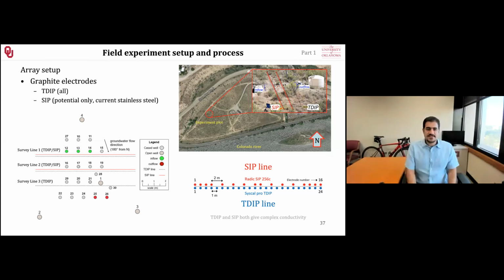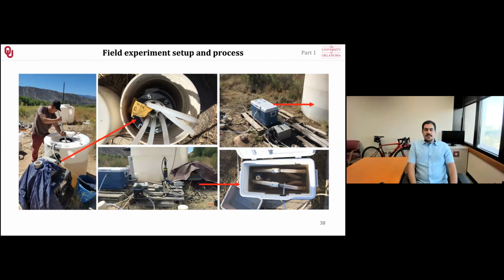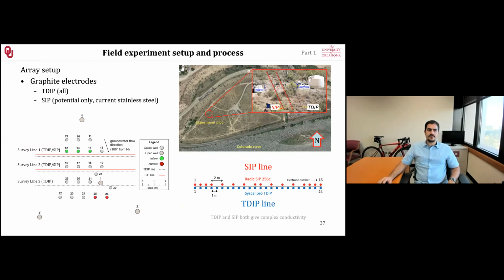What we did was basically, as you remember, I said the real conductivity or the resistivity is sensitive to changes in the electrical conduction through the pore filling fluid. So we withdrew groundwater from these two wells that are outside of our treatment area. We didn't use this one. We took water from the wells outside of our treatment area, mixed it with the ingredients that we had, and injected it back into the treatment area.